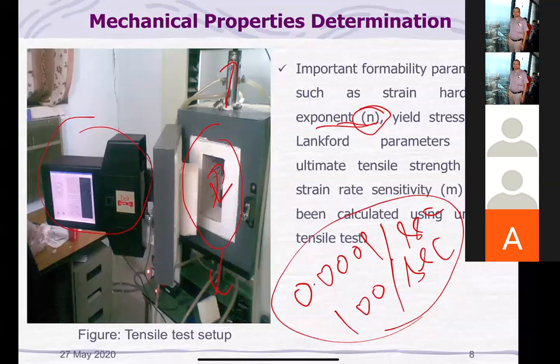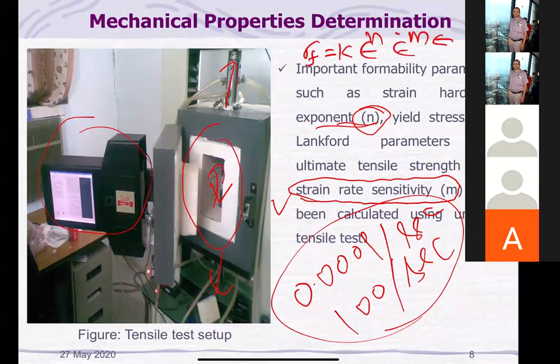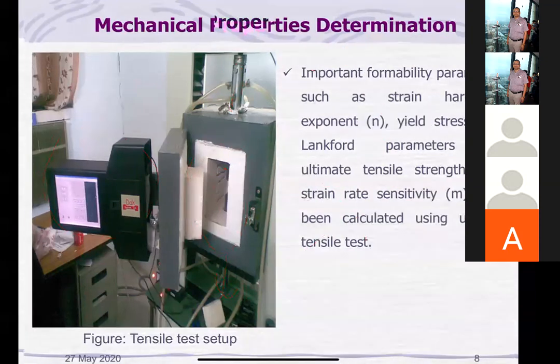It's quite a confusing question. Of course, formability depends upon many factors, but the most important factor is the work hardening exponent N, because it will suppress the formation of neck in the punch corner region. And because you are forming at elevated temperature, the strain rate sensitivity index M also plays a very important role. If you see the complete flow curve equation in a very basic form, it is sigma F equals K epsilon raised to power N, epsilon dot raised to power M. We are talking about this M, the sensitivity index. So these things are very important.